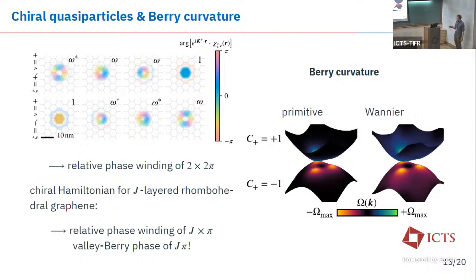And this is well reproduced within our Wannier functions, and the last thing to check is the Berry curvature, which arises due to those phase windings. And we see that, at least in a certain energy window, we really strongly reproduce all the features from the primitive cell model. So here on the left, you see the primitive cell Berry curvature, overlaid onto a 3D contour plot of the dispersion. On the right-hand side, you see the Wannier function Berry curvature, so the Berry curvature of the projected Wannier model, and you see that it agrees well in a certain energy range. So if you imagine you cut here and here, you see it's perfectly the same.